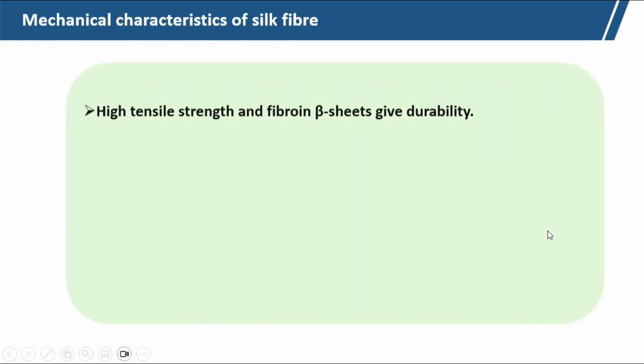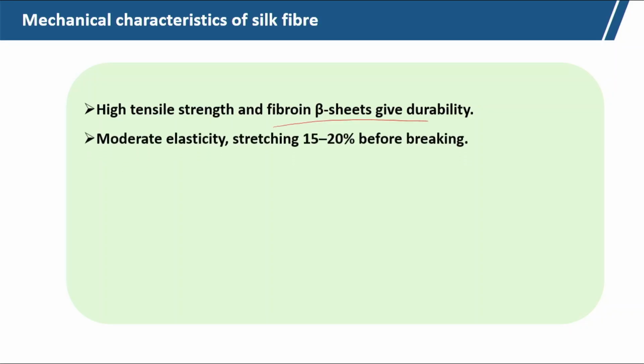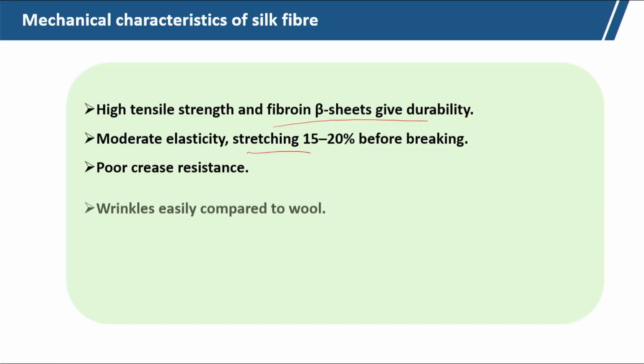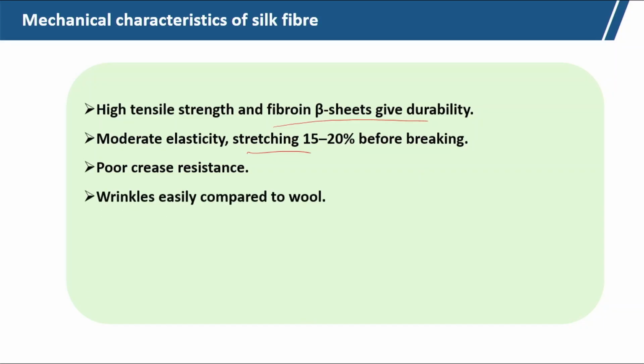Now, mechanical strength of silk is very good. So, high tensile strength, and the fibroin beta sheet gives durability. So, that is why in old days this silk fibre was initially used as a protective textile from mechanical threats. Moderate elasticity, stretchability is 15 to 20% breaking elongation. Crease resistance is poor, it gets wrinkled easily,